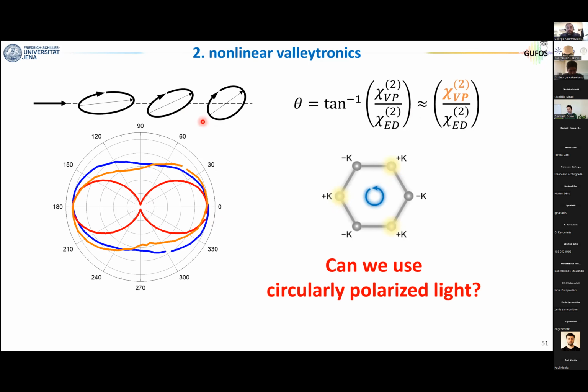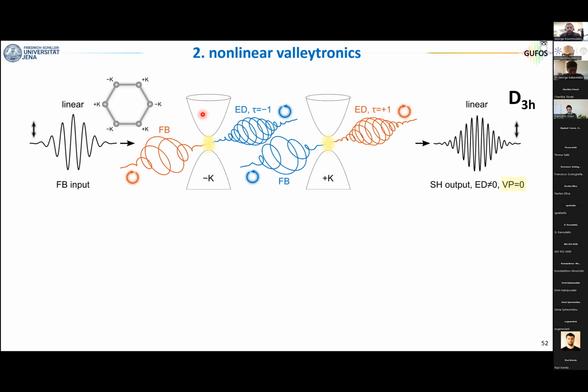With this method, certainly not, because the moment that we go circular, we cannot measure the rotation angle anymore. So we are lost. But what happens if we shine circularly polarized light? I want to explain the case with this sketch. Let's say that we start from a material that is at equilibrium, so no valley imbalance. We arrive with linear polarization. Linear polarization is a perfect superposition between left and right circular polarization. Each of them will excite one of the two valleys in a perfectly balanced way. Time reversal symmetry is preserved. The output will be linear.